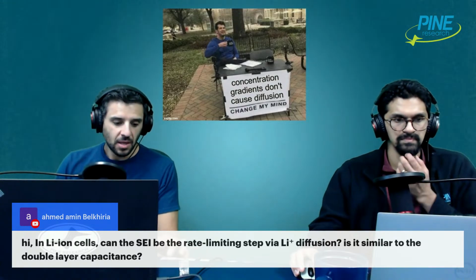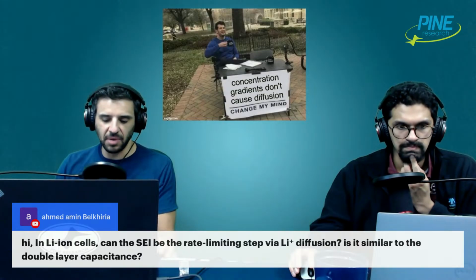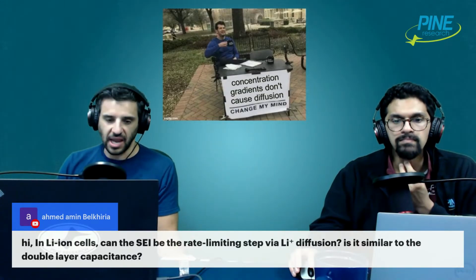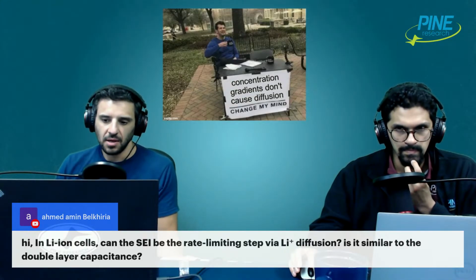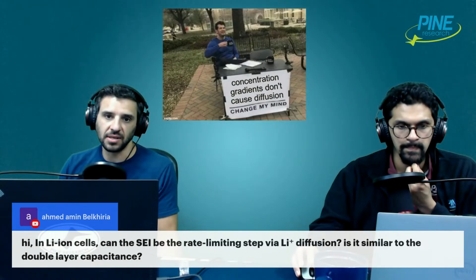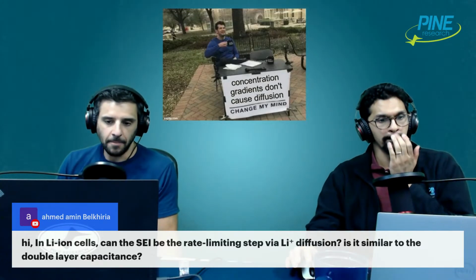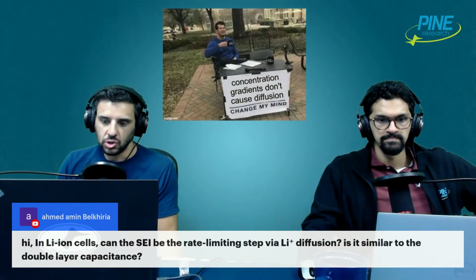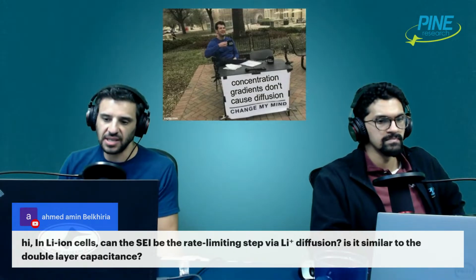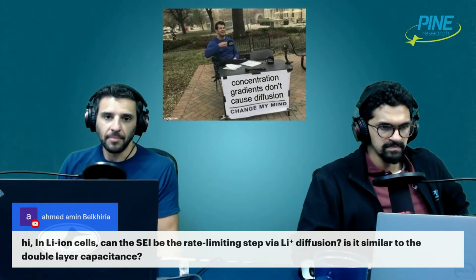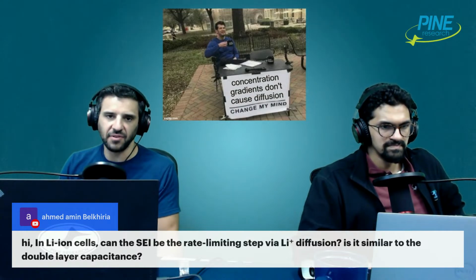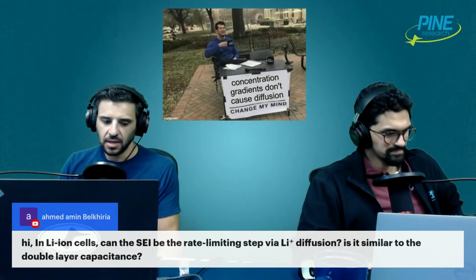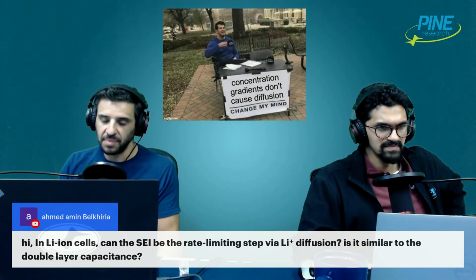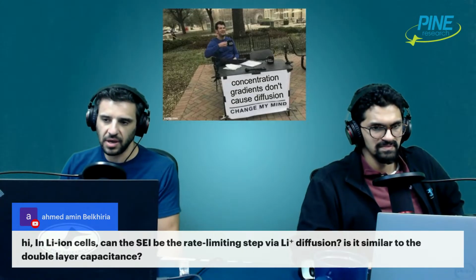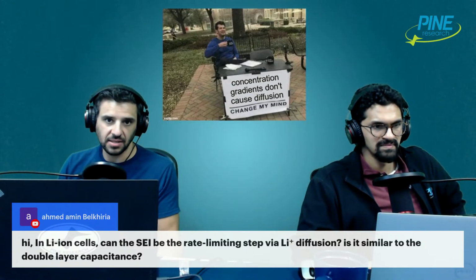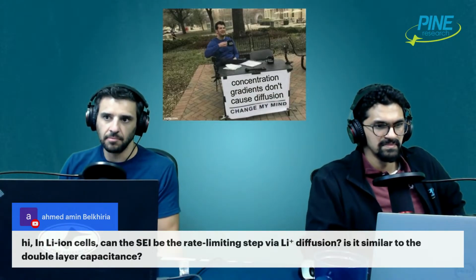There's a similar phenomenon, in much the same way that in standard solution phase electrochemistry, basically electron transfer cannot occur until the double layer has set up. Effectively, in a lithium-ion cell, discharge is not going to occur until the SEI sets up as well. It must set up. And the SEI is one of these really fun and baffling concepts, because one of the dangers of batteries is that you can decompose the electrolyte, causing thermal runaway. And the SEI protects against that kind of decomposition of the electrolyte by decomposing the electrolyte.